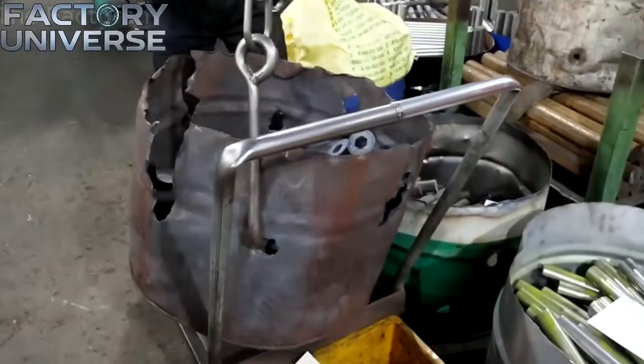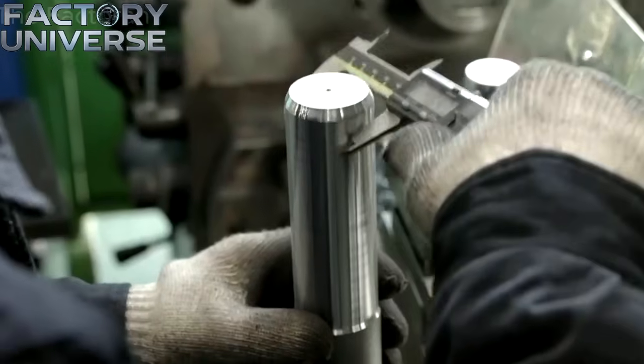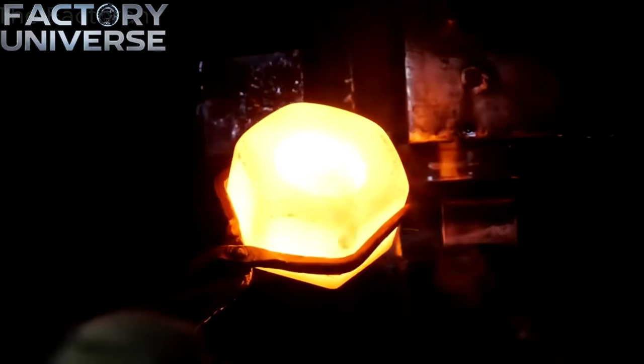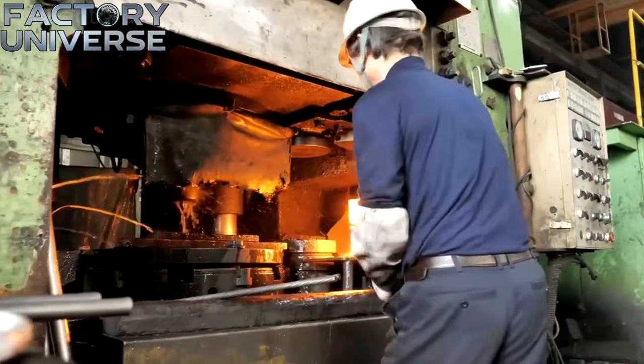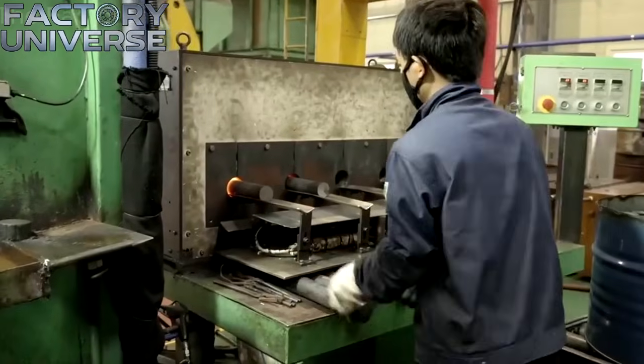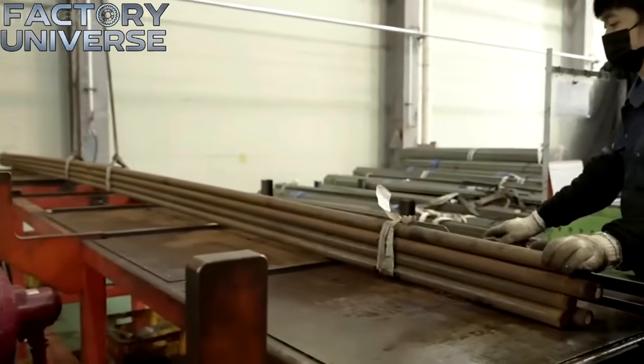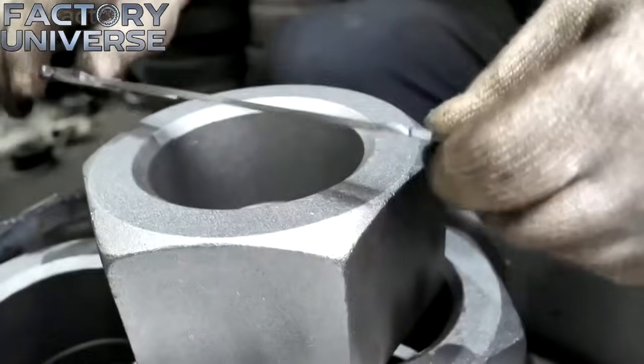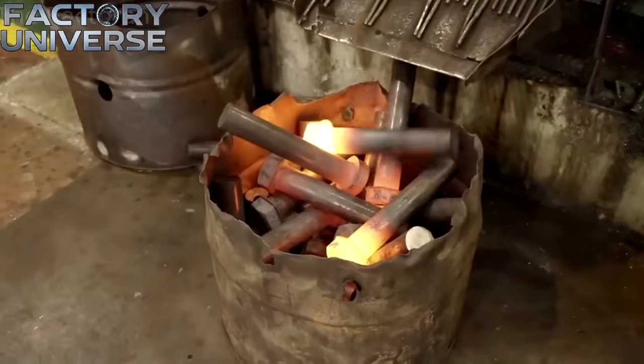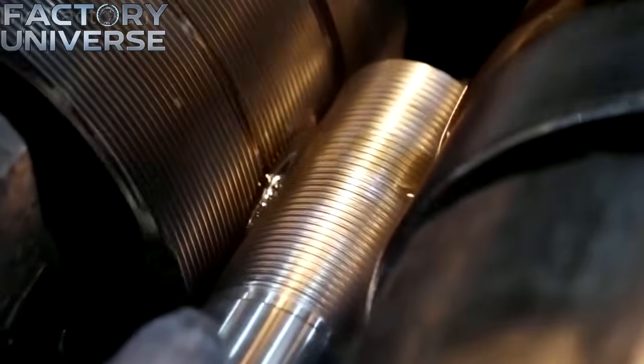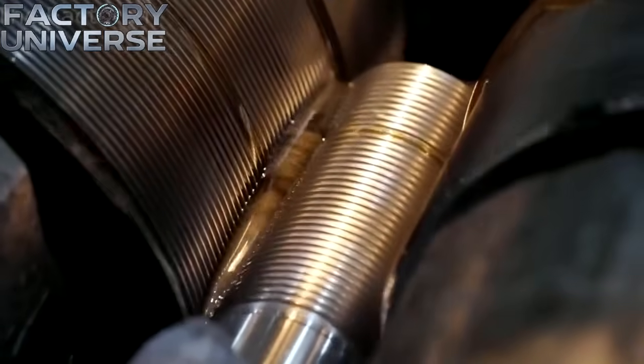In this stage, the shank passes between two hardened rollers that contain the thread profile. The metal is not cut, but rather plastically deformed and forced to rise into the shape of the threads. 3 seconds is all it takes for the smooth shank to be transformed into a system of sharp, uniform threads. This rolling method creates a much stronger thread than traditional cutting because the grain flow of the steel remains continuous.